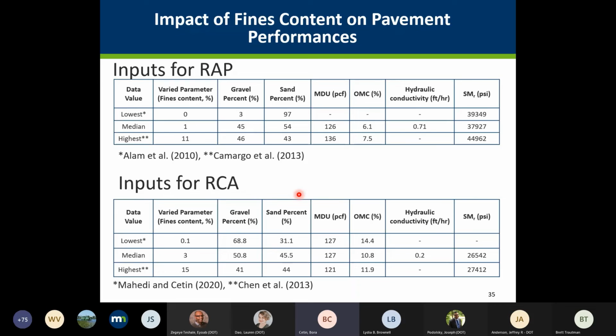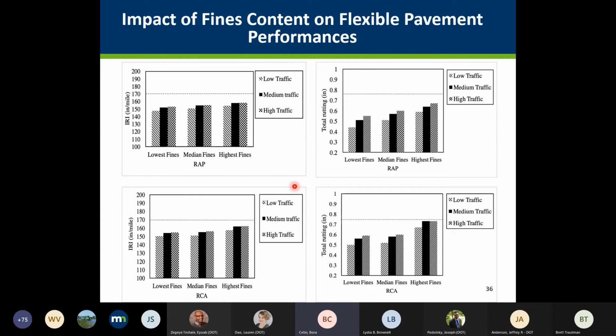And again, we look into the pavement distress predictions, and with an increase in fines content, regardless of the traffic conditions and pavement distresses, an increase in fines content causes an increase in the IRI and total rutting values as expected. And again, even at higher traffic conditions, though, with all these materials at this wide range of high fines content, the system did not fail in terms of IRI or total rutting under these pavement structural conditions and the data that we use for RAP and RCA materials.